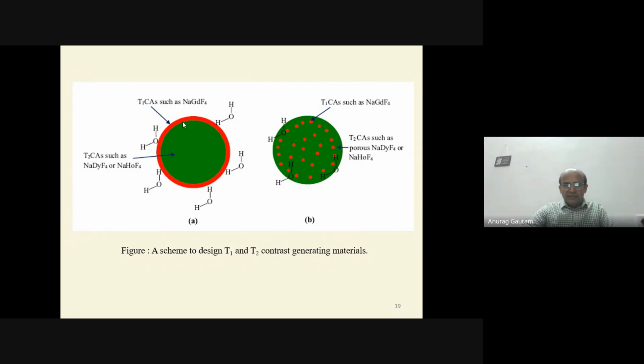So here we coat this gadolinium on the surface, and we keep a sodium dysprosium fluoride core or sodium holmium fluoride core. Both have a magnetic moment of 10.4 mu B for one atom. If the number of ions is 100, then we multiply by that. So that will be very, very high mu B, Bohr magneton. Here, this is one way.